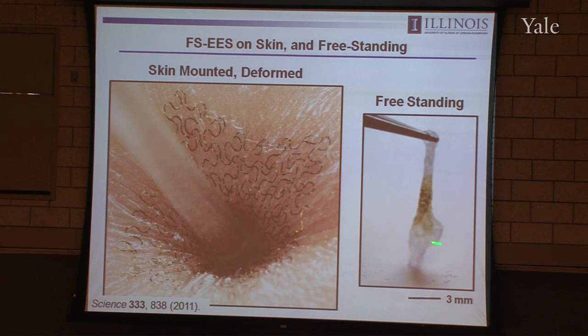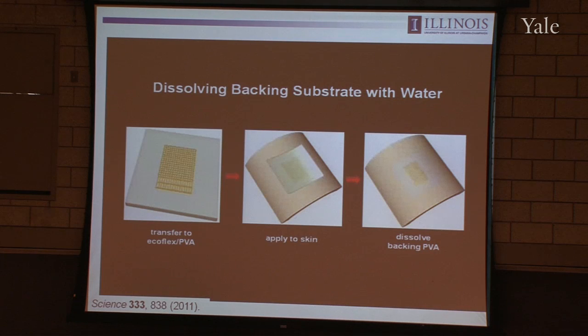And so the question is, how do you even handle this thing in order to mount it on the skin in the first place? And the way that we do that is just go back to kids' temporary tattoos, which oftentimes involve a water-soluble backing layer. And so we use PVA in this case. Laminate the epidermal electronics on top of that. Then you can use the PVA as a handle, slap it on the skin, and then wash off the PVA, just leaving the epidermal electronics on the skin. I'll show you a movie of that process. Here you can see it.